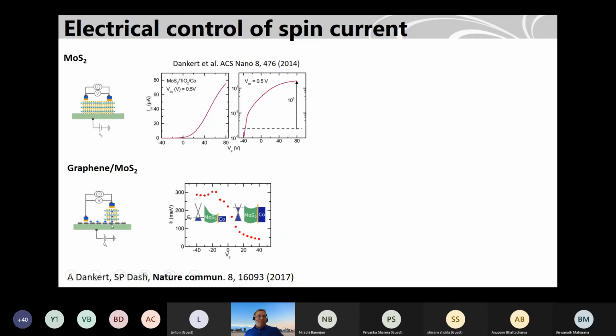And again, another thing: between graphene and MoS2, there is a Schottky barrier. MoS2 is a semiconductor, graphene is metal-like, but it's a tunable metal. So when you apply gate voltage, you tune the Fermi level in graphene, going from the valence band to the conduction band. When you do that, you are changing the Schottky barrier height between graphene and MoS2, and it goes from, let's say, 300 millielectron volts to almost 25 millielectron volts. So at room temperature, there should be no barrier.